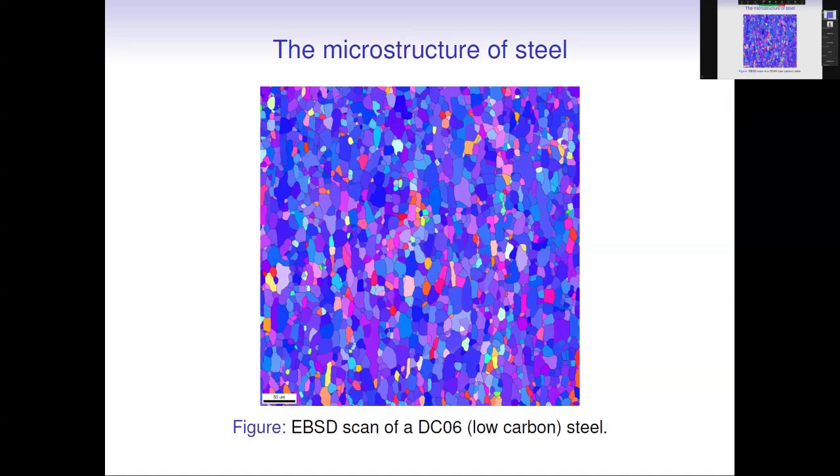For every grain, they assign material properties like elasticity and plasticity properties, and then they perform tests like stress-strain tests or shearing tests. They want to know how the microstructure influences the macroscopic properties. That's the goal at the end of the day. They also do things like grain growth, where they have lots of snapshots in time that they want to interpolate between. At the end of the day, it's about developing new alloys and understanding how the microstructure affects the macroscopic response, and it has a huge effect.